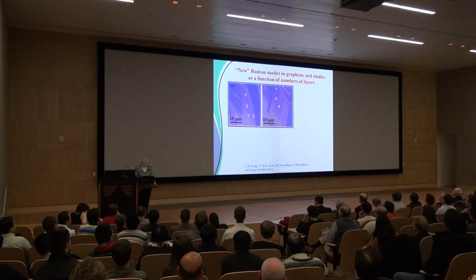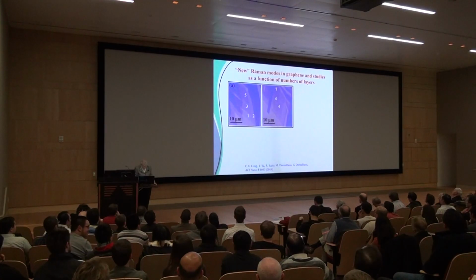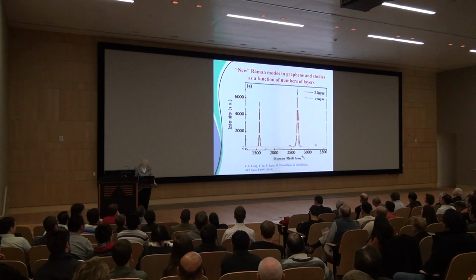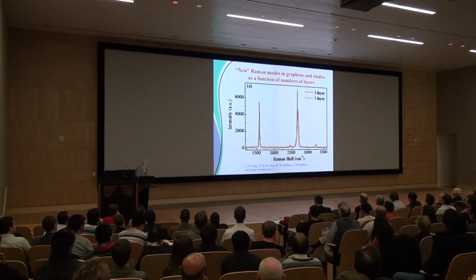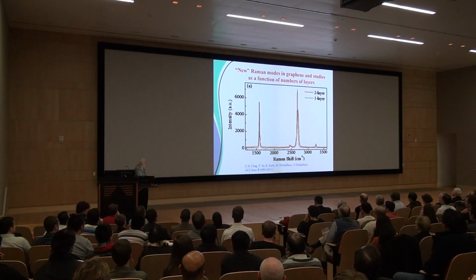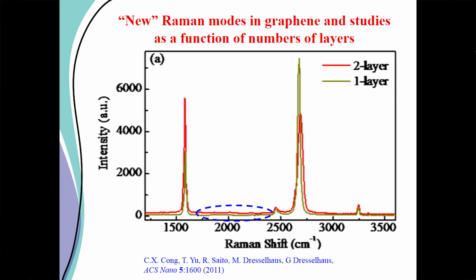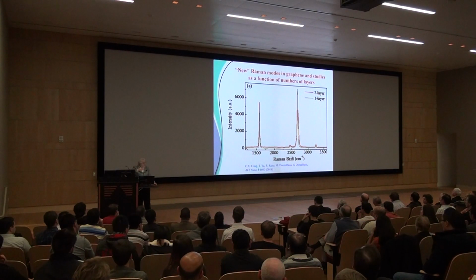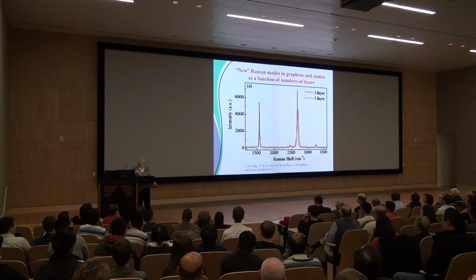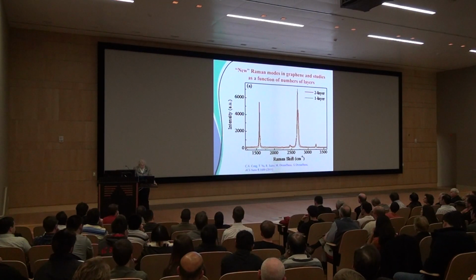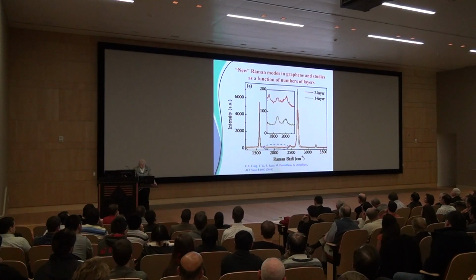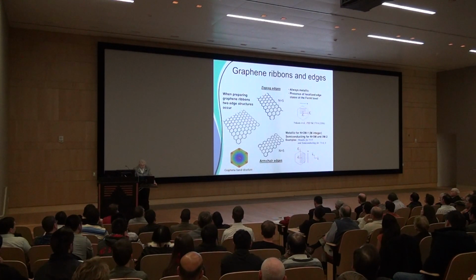And you can make many layers, and each layer has interesting properties. So we have been studying this reference. We still work on that. And some of the interesting things that happen with that is that we can study all the different combination modes. And they occur here. There are little tiny wiggles here, but they have interesting symmetry properties. And if you vary the Fermi level by changing the laser energy, something like that, and changing the doping levels, then you can do many things and study those combination modes. And that's what we're doing at the present time. That's one of our research areas. Yeah, the spectra doesn't look so great, but if you persist and take many traces, then you get nicer lines.